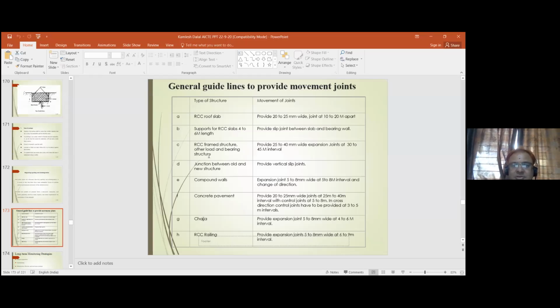In an RCC frame structure, under load-bearing structure, provide a 25 to 40 mm wide expansion joint at 30 to 45 meter interval. Why am I telling this? If a crack is there, then you can understand. If it is not provided, then cracks will be there. To prevent cracks, we have to provide such joints.